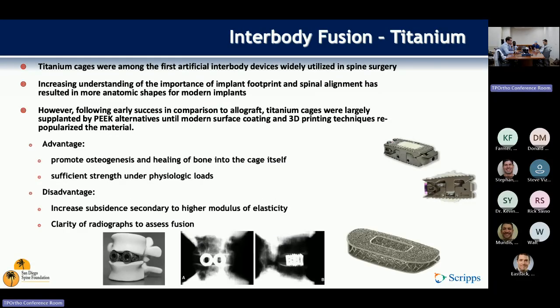So we're going to look at titanium cages first. Titanium cages promote osteointegration and are biomechanically favorable, but are certainly stiffer than bone, despite having a Young's modulus which is fairly close. This can cause subsidence and stress shielding, and they also do produce image artifacts, as we've seen getting post-op imaging. Shape and surface features like porosity can mitigate some of these issues, and 3D printing allows for greater customization, but still, nonetheless, is an issue we face.